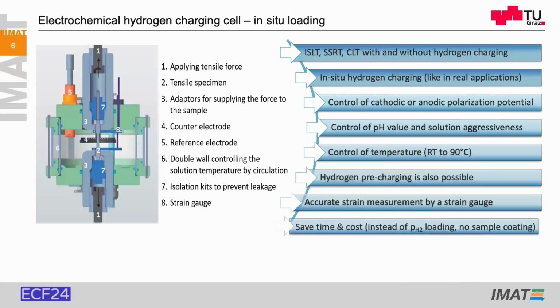Yeah, this is our development. It's maybe not really new. It is an electrochemical cell which is implemented in a tensile test machine. And you see here just a tensile sample of the rod steel, the counter electrode, and the reference electrode to get a stable loading current or a constant potential for the hydrogen in situ loading.